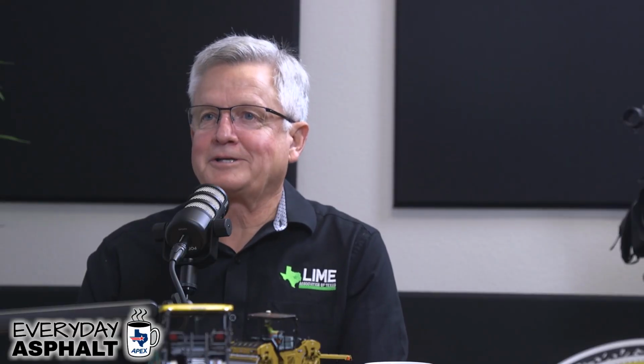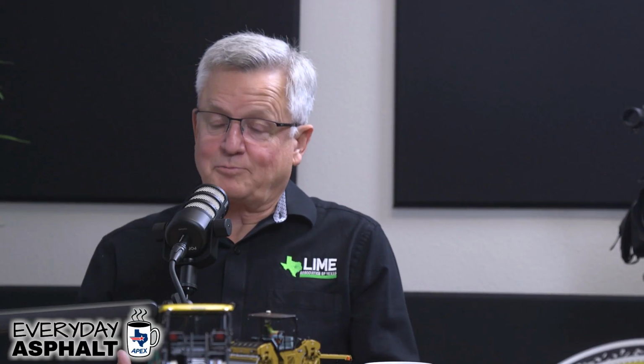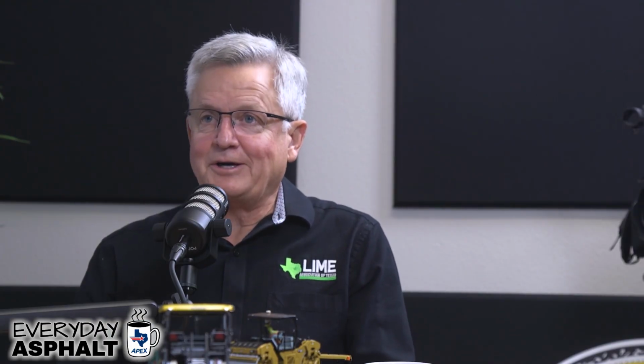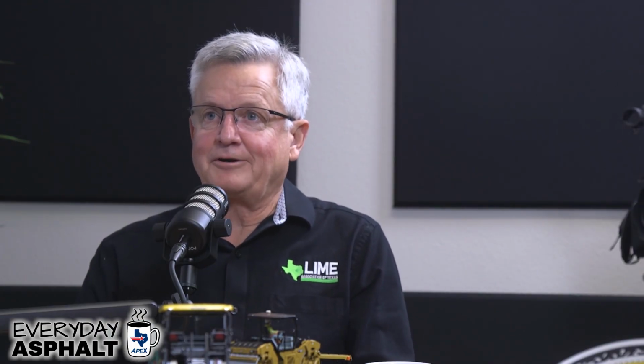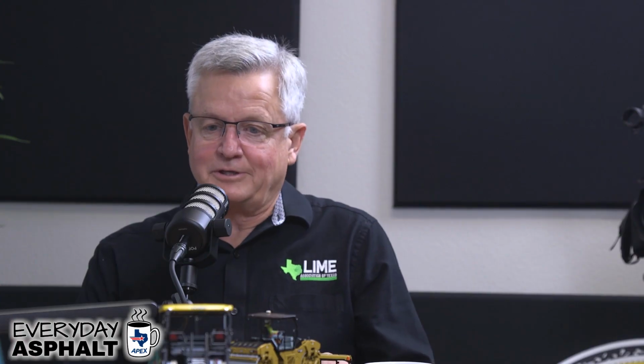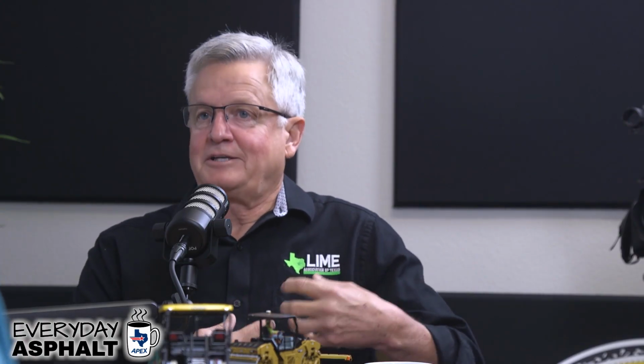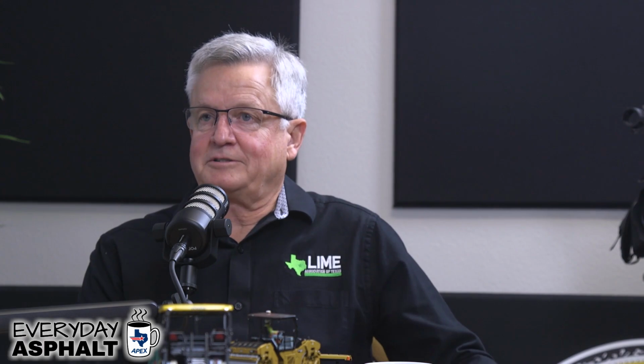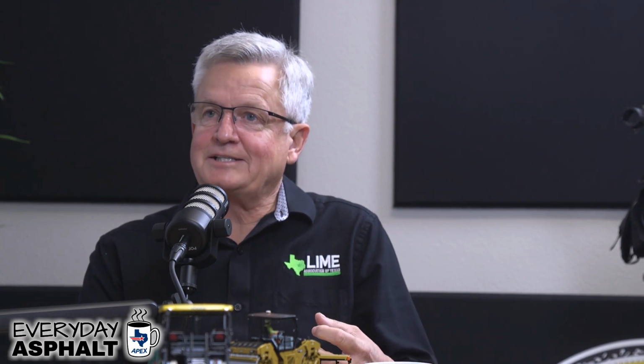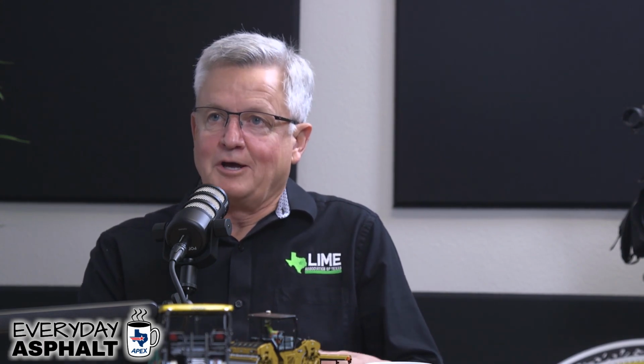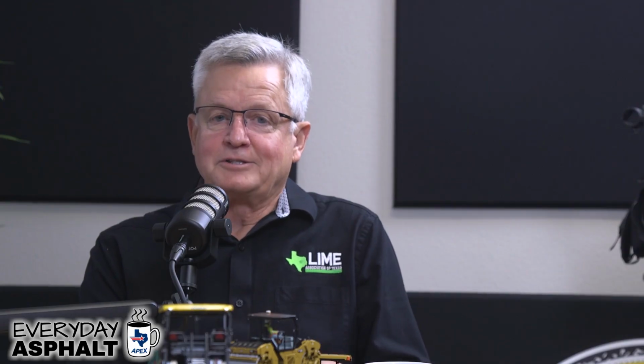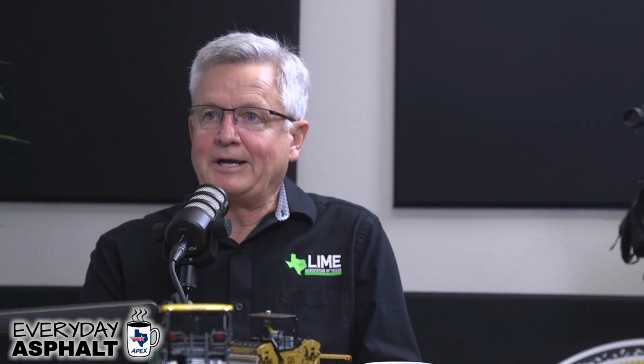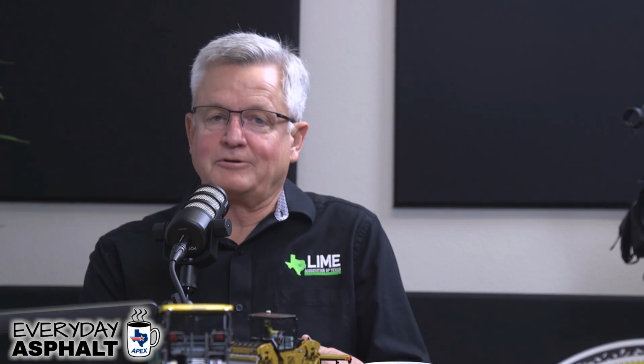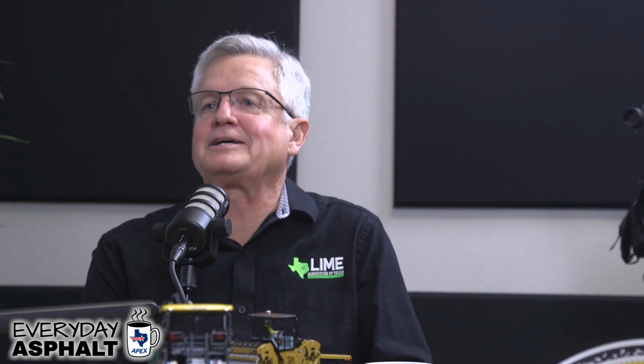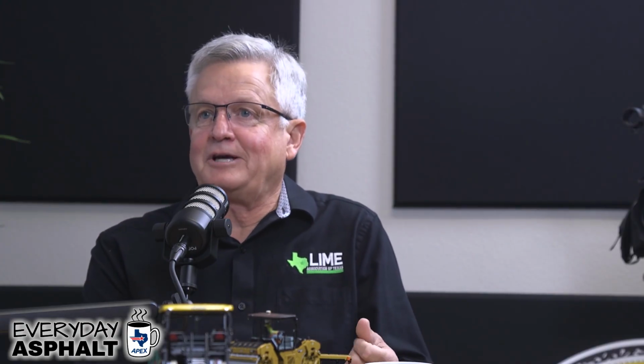Yeah, because it's pretty important. Texas is probably the only one that calculates VMA the way that we do it. And I'll get a little bit of background on it, because in Texas, we use the rice specific gravity to back calculate VMA, which really takes into account the absorbed asphalt plus the air voids. So our VMA numbers technically will be higher than any other state. The more absorptive the aggregate is, technically you can get more asphalt into that.